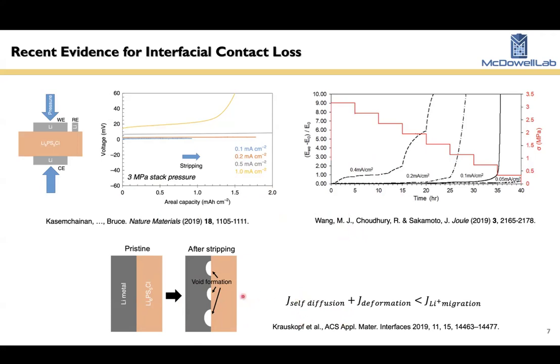But the idea is that if you're stripping lithium too quickly, if your migration of lithium through the solid electrolyte is faster than either self-diffusion or mechanical deformation of the lithium electrode itself can fill in these vacancies that are forming, then you by necessity will have vacancies that coalesce to form voids at the interface. And again, these voids represent a loss of contact and cause much higher impedance and cell failure eventually.